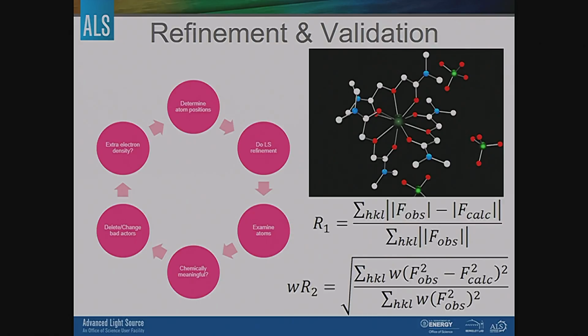They go through, and the scattering factors that we've got, our reflection list, is compared to a theoretical scattering factors list that your current atom positions make. Then they are compared. That's where you get the R values. So an R value is a comparison between the observed and our calculated. If this was our structure, we would calculate what the scattering factors would be for the structure, compare them, and you get an R1.